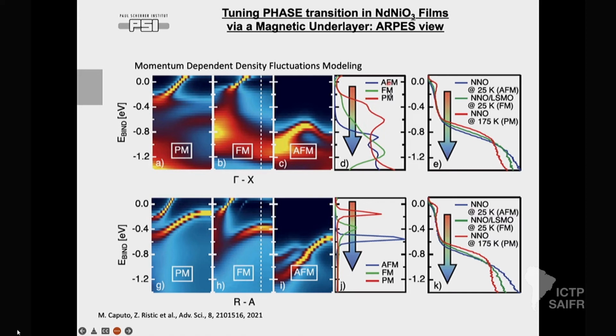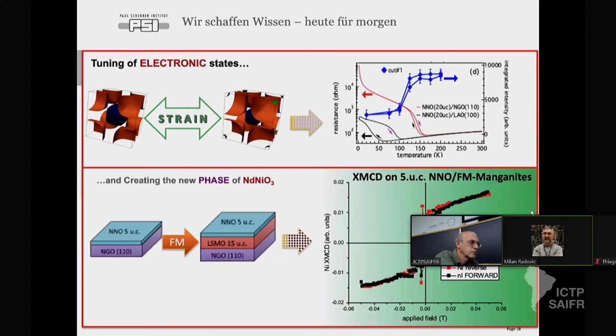If I'm now looking at the paramagnetic spectral weight at the Fermi level, versus the ferromagnetic, you could see there is a redistribution of the spectral weight, and in the experiment at very low energy, close to the Fermi level, we see this kind of shift. Red is up, green is down. So experiment and theory go well together.